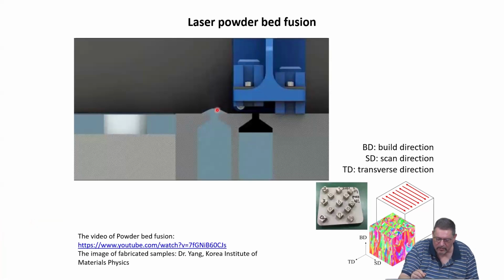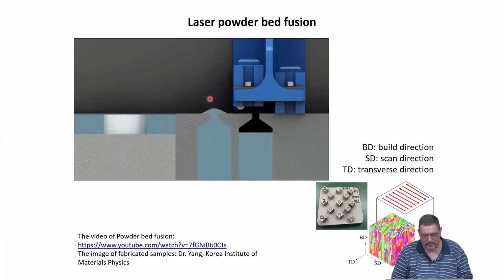Powder is distributed along this direction. Then this slider goes back with this one lowered. It basically scrapes off the powder which is too much. It falls here into this container so that it's not wasted. And then the laser comes down and melts the powder in the regions where it should be melted. And then the next powder is applied and so on. And so you build up these structures, as you can see here.